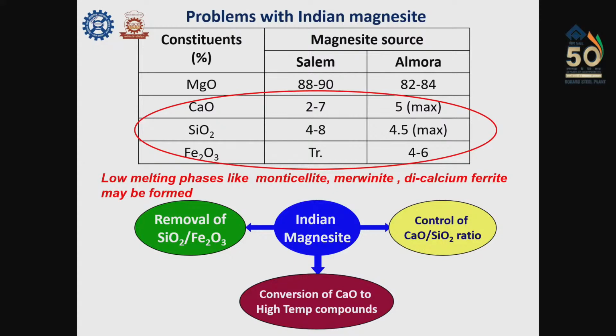There are several methodologies we can adopt for the value addition of this magnesite. First one is basically removal of silica or Fe2O3. There are several processes: flotation, physical separation, magnetic separation. And the third approach, we can convert the CaO to high temperature compounds, by which the available CaO can be reduced in the system for the low melting phase formation.